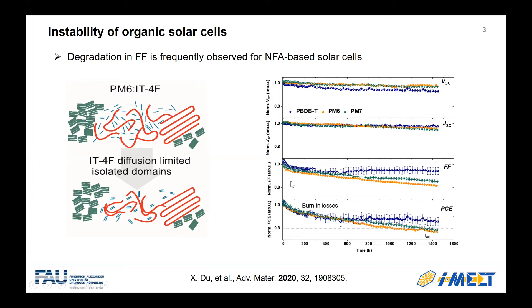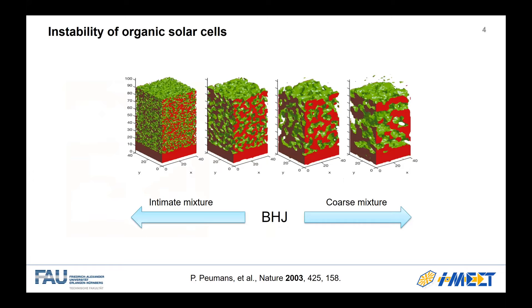This is a small degradation, but we consider it significant for long-term stability. For the bulk heterojunction concept, where we mix the donor and acceptor materials together and coat a single layer, the microstructure determines both device efficiency and stability. We have to optimize the microstructure for a given material system to get high efficiency, but high efficiency and high stability couldn't be achieved at the same time. We developed many concepts to address this microstructure-induced instability.